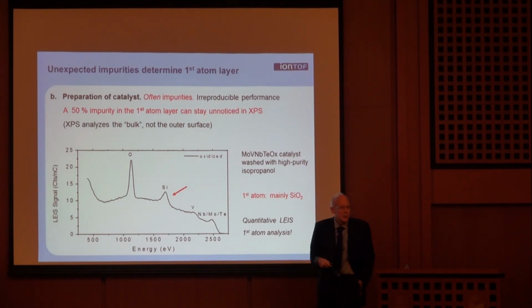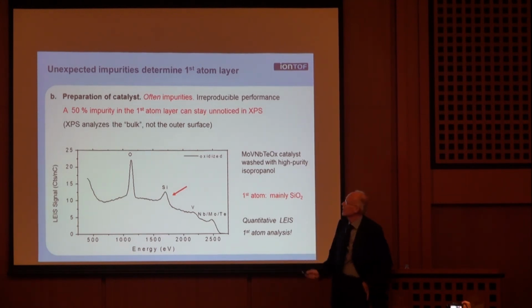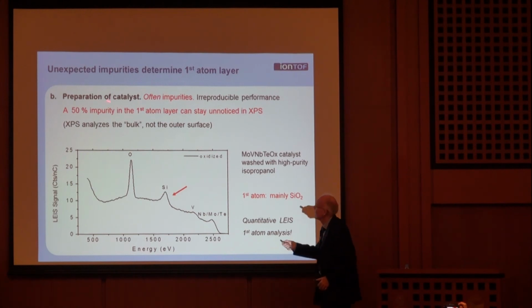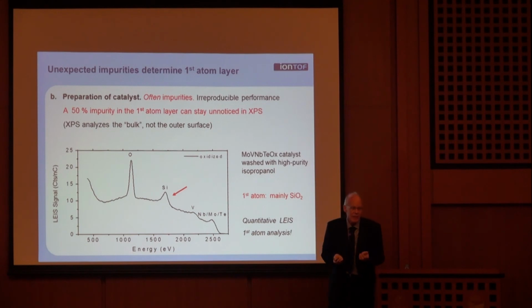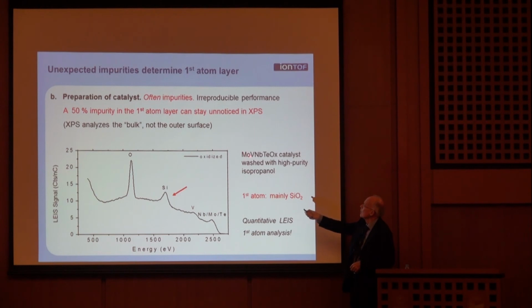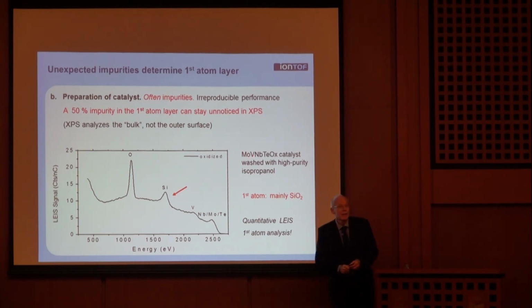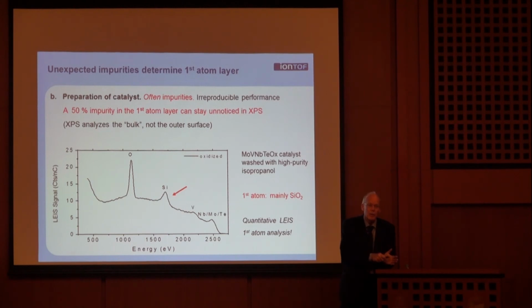First, I show you the bad examples, so the terrible things of contamination. This is an example of preparing a catalyst. And one of the ways of preparing a catalyst is that you impregnate them. And in this case, it was a very famous catalyst of molybdenum, vanadium, niobium, tellurium oxide for oxidation of propane to acrylic acid.